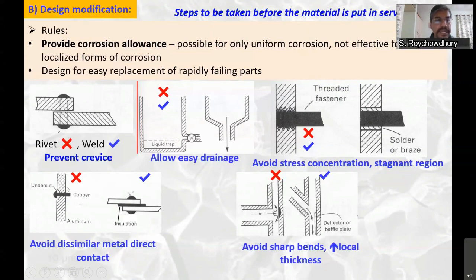Avoid dissimilar metal contact. Wherever you have dissimilar metal contact, one becomes the anode, the other becomes the cathode, and the anode corrodes, which is not good. So try to provide insulation to break the electrical contact between two dissimilar metals. Avoid sharp bends and rapid changes in flow direction. Like in this case, these regions will be prone to impingement attack or erosion corrosion. So rather make a design like this, so the flow gently mixes with this flowing stream and there is no impinging action here. You can also provide some additional thickness here, a deflector or baffle plate, that will increase the life of this component.